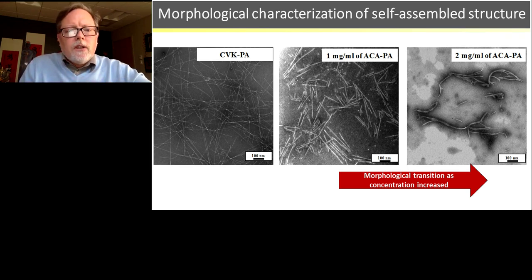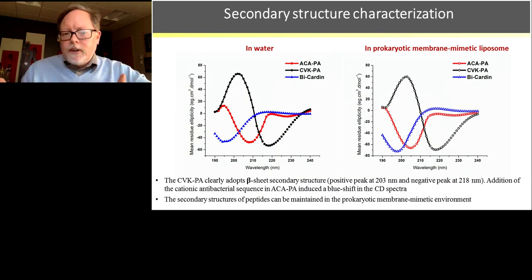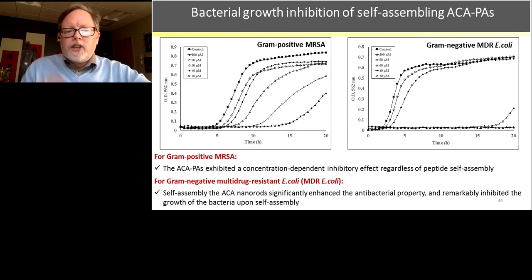Here's what these structures look like. Again, you can see these nanofiber formations. Of course, if you increase the concentration of these self-assembled materials, you'll get longer and longer chains. So we need to have the right concentration that will penetrate that bacteria wall. We confirmed secondary structure to show that each one of these three materials is the structure we think it is. And most importantly, what I want to share with you is the ability of these materials to reduce bacteria growth.